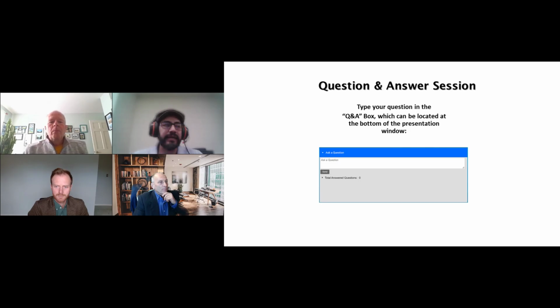Yes, indeed. This actually comes from the previous answer. One of the problems for the reproducibility of SERS systems is the shape and the distances between the nanoparticles in order to induce this enhancement factor. However, when we have graphene, as it is a flat layer on top of the quartz substrate, we have tested different points at different positions of the graphene lattice, and we obtain the same result. There is a dependence only on the presence of the molecule we want to study.